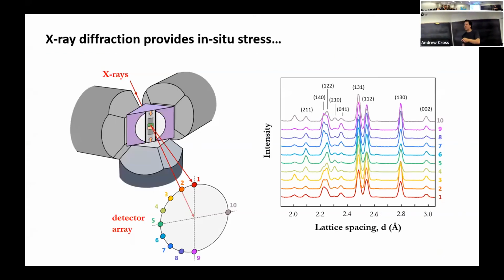So what this means is we've got X-rays passing through the gap in the anvils, through our sample, and then they're being detected downstream by 10 detectors arranged in an array like this. At each one of these detectors, we get an energy dispersive X-ray diffraction pattern. So we've got different colors for the 10 different spectra, one for each detector.